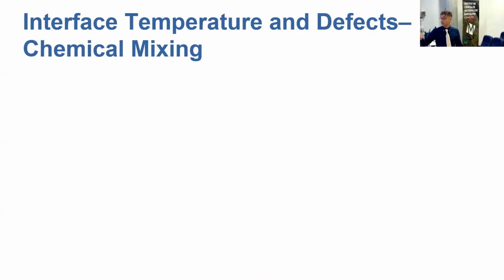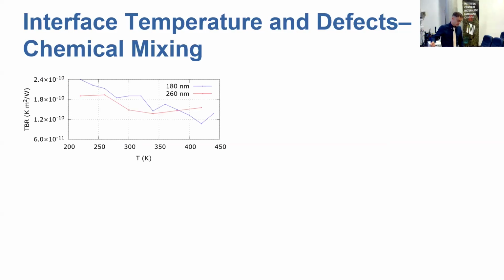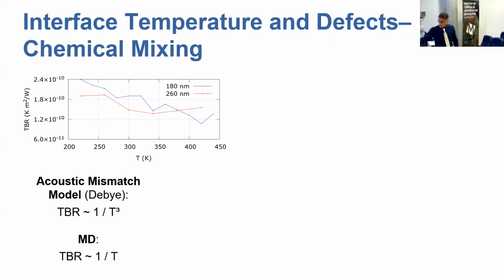So, interface temperature, as the name says, corresponds to varying the interface temperature of the junction. So we apply a parallel shift to TA and TB up or down, and we repeat the whole simulation, and we see how the TBR depends on the interface temperature of the junction. We also did the simulations for 2 different junction lengths because we wanted to make sure that our results did not really depend on the junction length, and the results confirmed that we already had achieved convergence at 180 nanometers. And the interesting fact is that from our simulations, we derived a dependency of the TBR on the interface temperature, which goes like temperature to the power -1.